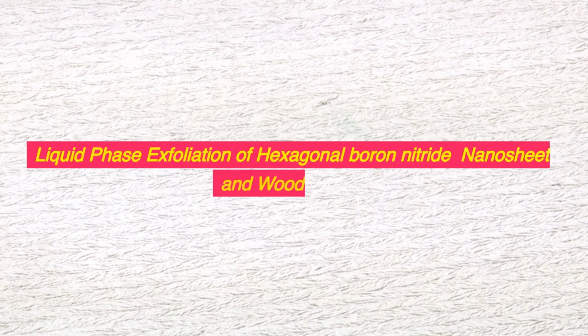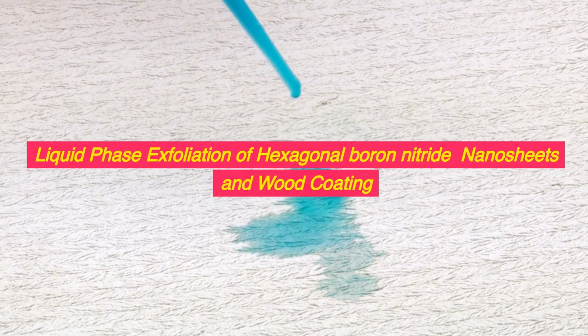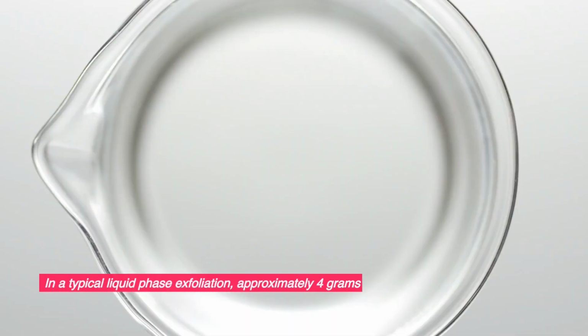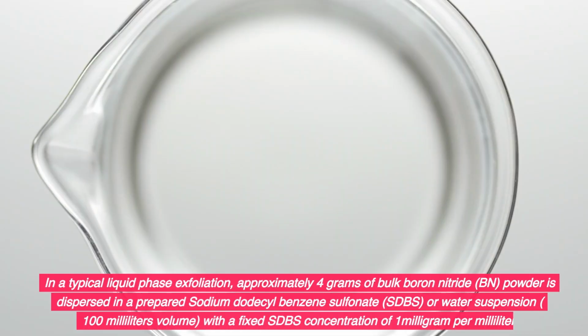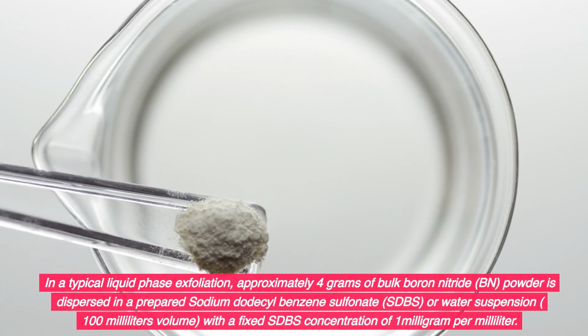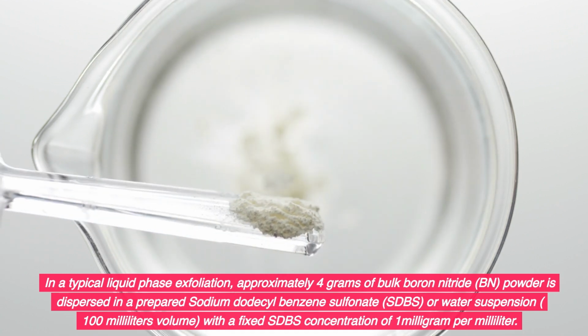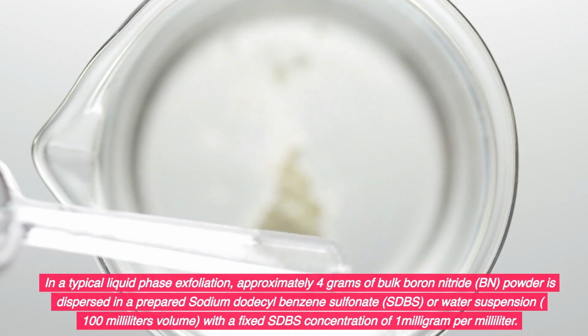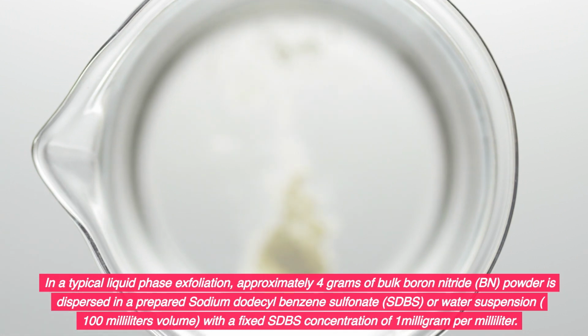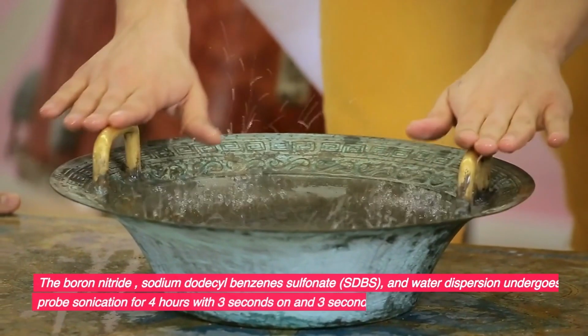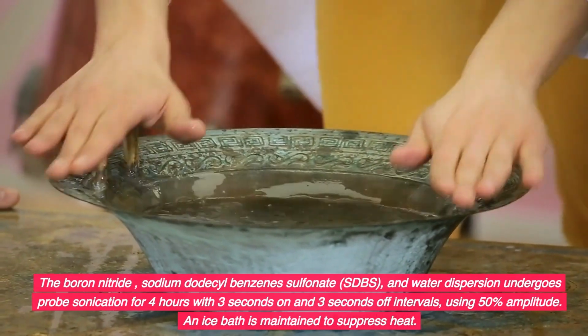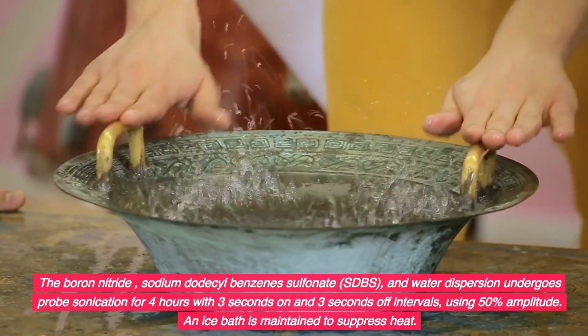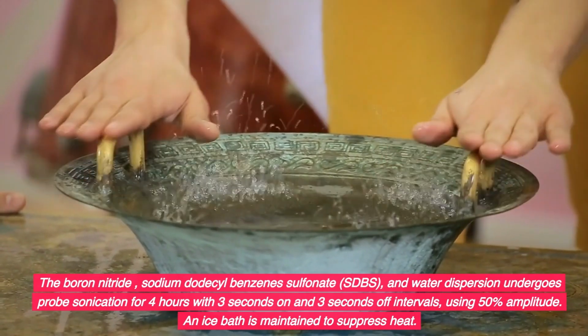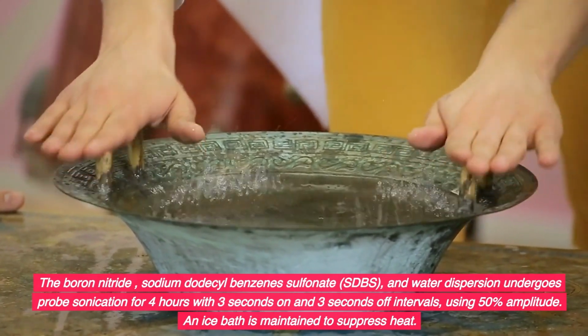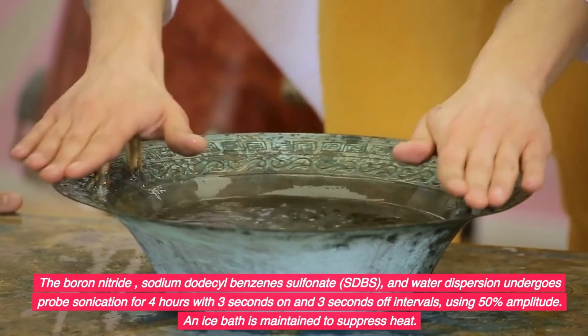Liquid phase exfoliation of hexagonal boron nitride nanosheets and wood coating. In a typical liquid phase exfoliation, approximately 4 grams of bulk boron nitride (BN) powder is dispersed in a prepared sodium dodecyl benzene sulfonate (SDBS) or water suspension, 100 milliliters volume, with a fixed SDBS concentration of 1 milligram per milliliter. The boron nitride, SDBS, and water dispersion undergoes probe sonication for 4 hours with 3 seconds on and 3 seconds off intervals using 50% amplitude. An ice bath is maintained to suppress heat.